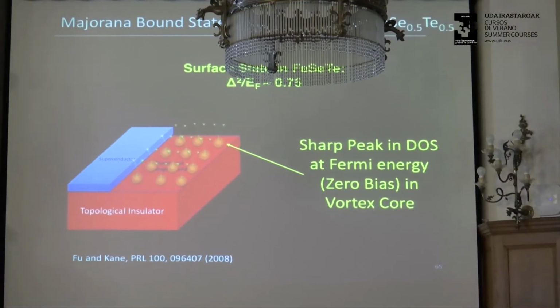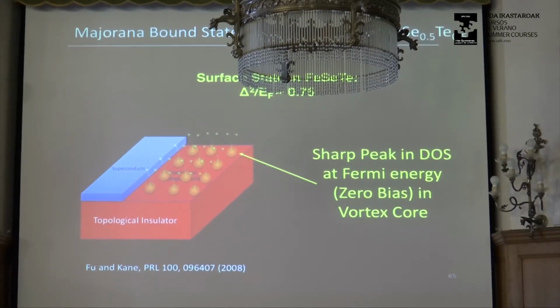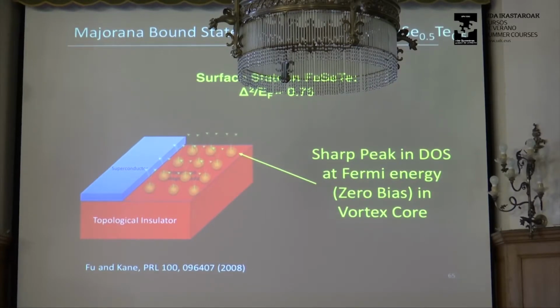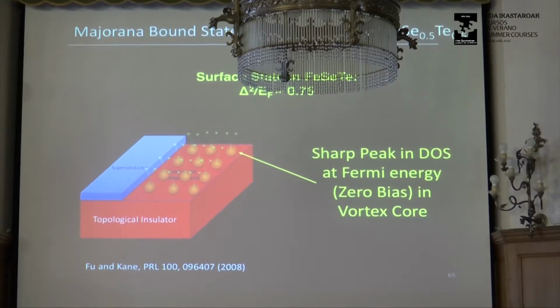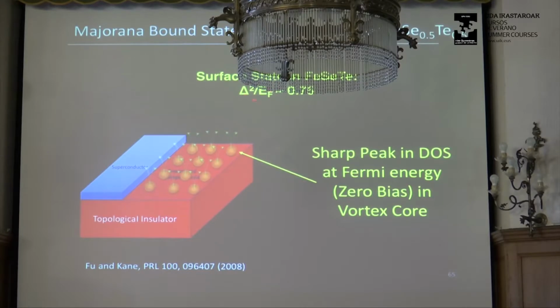So delta squared over EF tells you, if you have trivial Caroli-de Gennes-Matricon states inside the superconducting gap, the energy where the first one would appear. For this system, for the surface states, you can calculate delta squared over EF, and it is about 0.75 meV. So 750 microvolts is where the first non-trivial bound state should appear inside the gap. So there should be nothing really at 0. If you have the resolution to distinguish between 0 and 750 microvolts, you should be able to see whether the system has Majorana bound states.